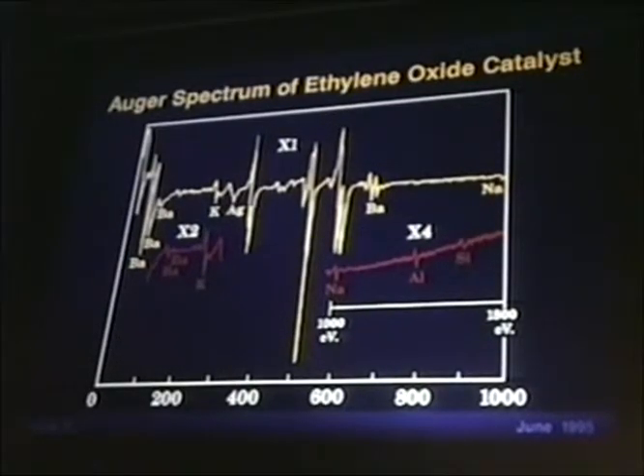Thus, the performance of these batches was found to be a result of the varying amount of these impurity elements coming either due to processing or preparation conditions, coming out of the support and later getting deposited on the surface of silver, which is the one doing all the catalysis, and acting as poisons. These elements, sodium and potassium, are known to be promoters as well, as long as they are present in near optimum amounts. However, they are poisons in larger amounts beyond the optimum.